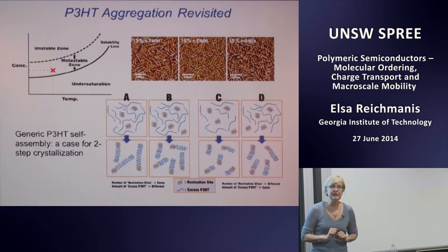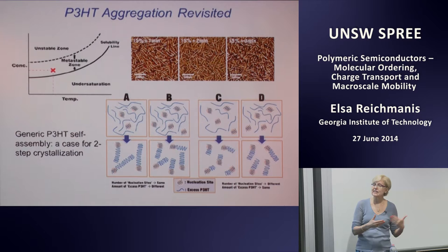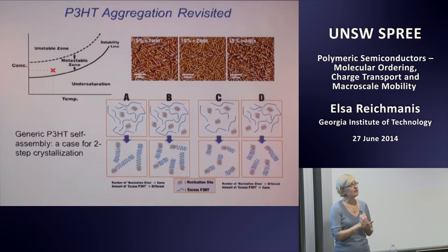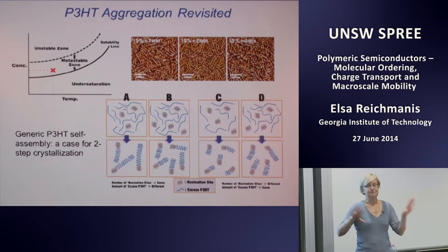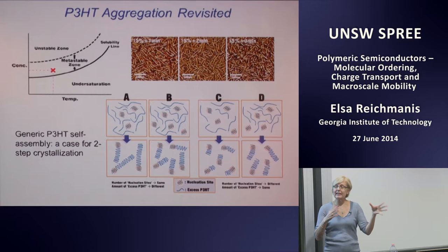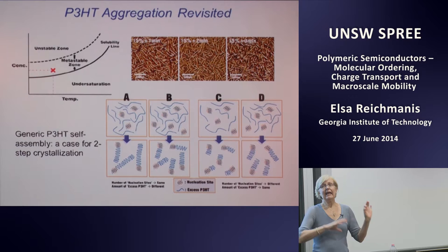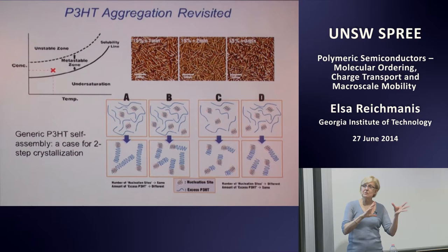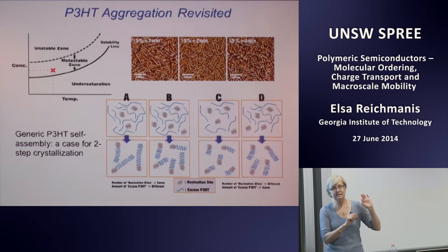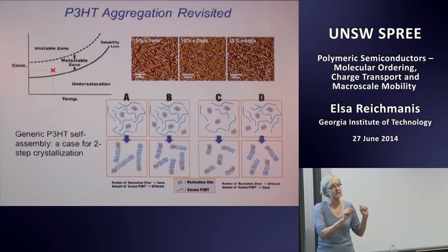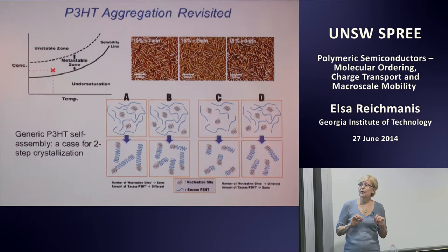And what my student has been looking at in the case of P3HT here is to bring this now back to a traditional two-step recrystallization model, where there's an element of nucleation followed by growth of the P3HT aggregates or nanocrystallites. And so if we can balance the proportions of non-solvent followed by the ultrasonication treatment, we can optimize the number of crystallites or recrystallization sites, nucleation sites being formed in solution, and still have a sufficient level of poly-3-hexylthiophene left in the solution that is available for growth from those crystallite chains.